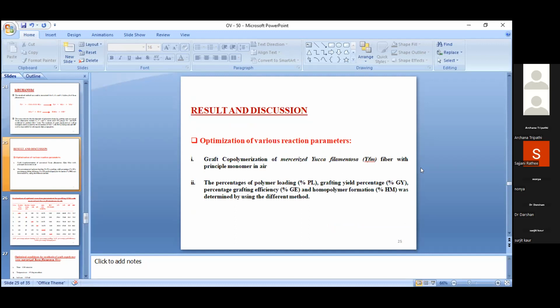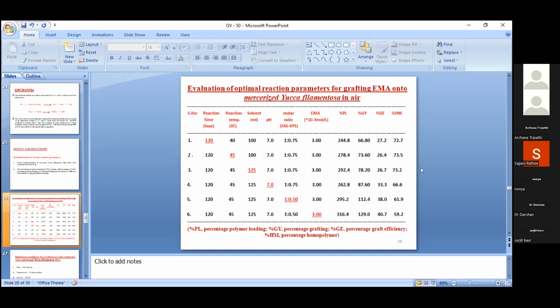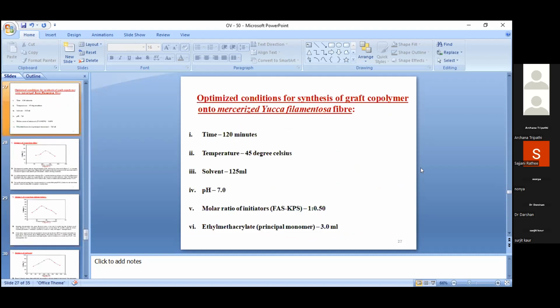Optimization of various reaction parameters is followed by graft copolymerization of mercerized yucca filamentosa fiber with principal monomer in air. The percentage of polymer loading, graft yield, percentage grafting efficiency, and homopolymer formation was determined using the standard method. This table presents the evaluation of optimization parameters for grafting EMA onto the mercerized yucca filamentosa in air. You can see in this table the percentage graft yield is increased as we optimize the different reaction parameters. These are the optimized conditions for synthesis of graft copolymer onto the mercerized yucca filamentosa fiber. The time is 120 minutes, temperature 45 degrees Celsius, solvent 125 ml, pH 7.0, molar ratio of initiator, that is FAS to KPS, 1:0.50, and ethyl methacrylate, that is the principal monomer, 3 ml.